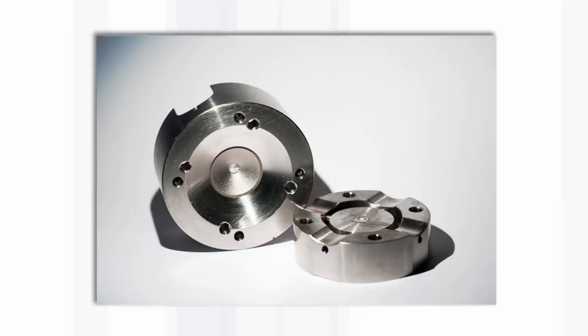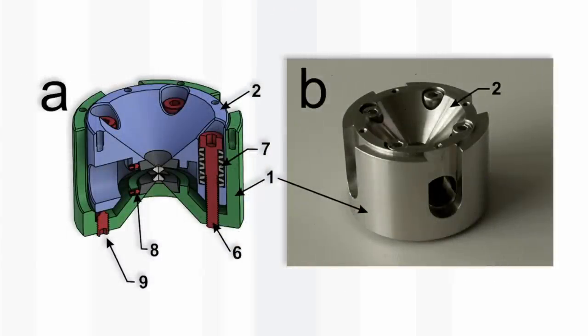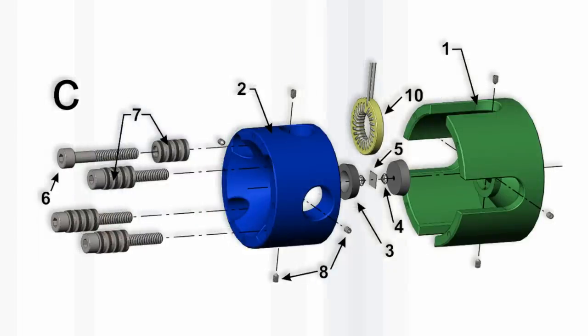In that hole is where they did the experiment. They fill it by putting a very high pressure of nitrogen — about 1,200 atmospheres — around the whole apparatus. As they start squeezing, the nitrogen solidifies. When it's solid, it's not very compressible, so they can ramp up the pressure very easily. That's how they get to 1.4 million atmospheres.